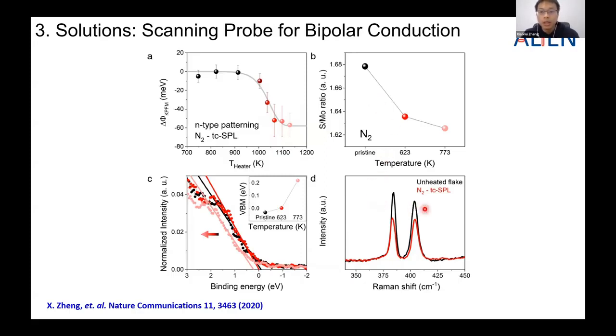of the sample, and we also use the Raman spectrometer to characterize that the n-type doping has been achieved in the material, and also XPS. It is well known the n-type doping is a result of sulfur vacancies. So we believe that by using the hot tip to scan the sample in an inert environment, we are creating more sulfur vacancies, and these are the reason for the further n-type doping of the MoS2.